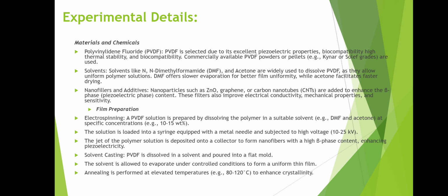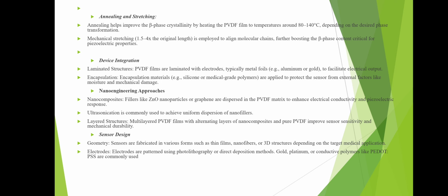As a result, the piezoelectricity will be increased. In solvent casting, the PVDF is dissolved in a solvent and poured into a flat mold, and the solvent is allowed to evaporate under controlled conditions to form a uniform thin film. Annealing is performed at elevated temperatures, 80 to 120 degrees Celsius, to enhance crystallinity. So what is the phenomenon that occurs in annealing or stretching? Annealing helps improve the beta phase crystallinity by heating the PVDF film to temperatures around 80 to 140 degrees Celsius, depending on the desired phase transformation, and mechanical stretching to 1.5 to 4 times the original length is employed to align the molecular chains, which increases the beta phase content that is critical for the piezoelectric properties.